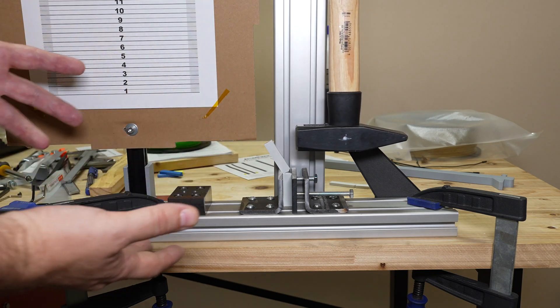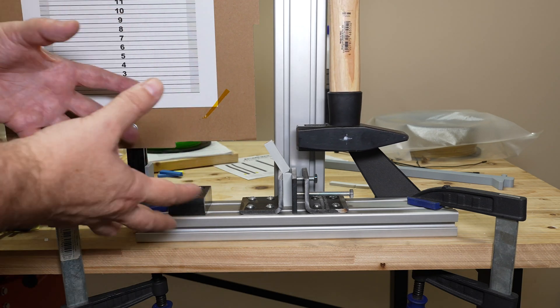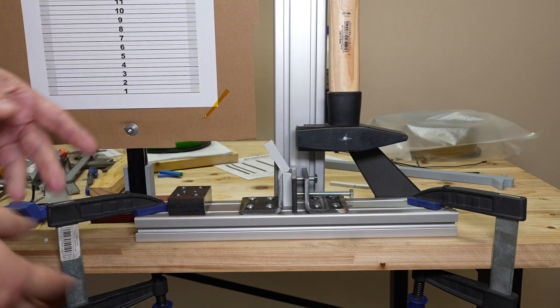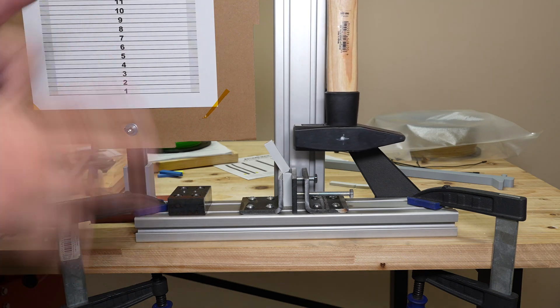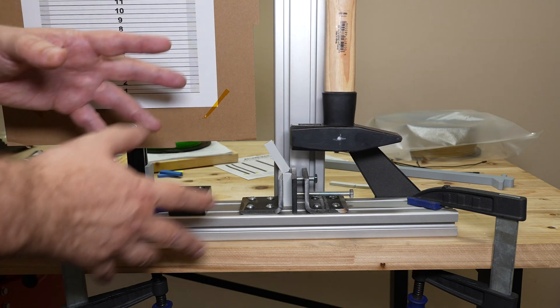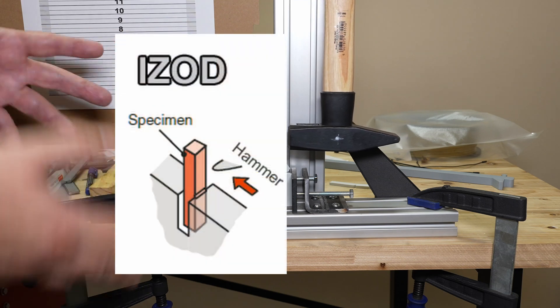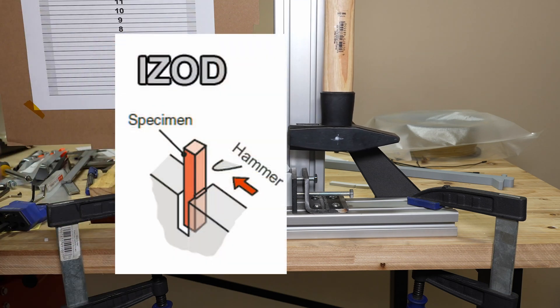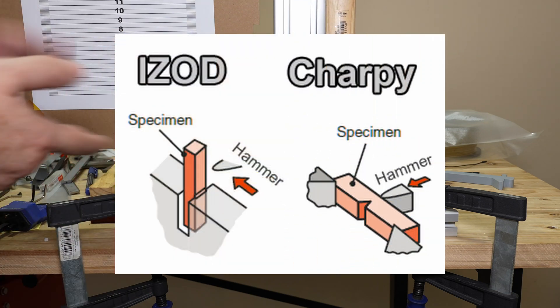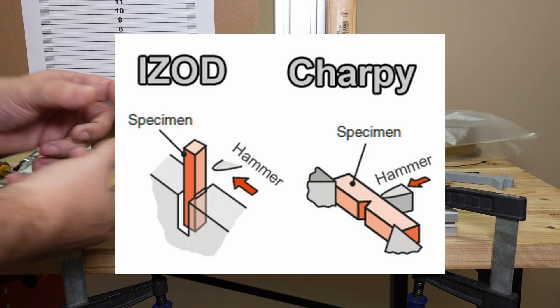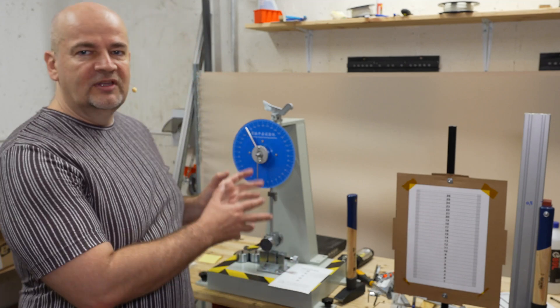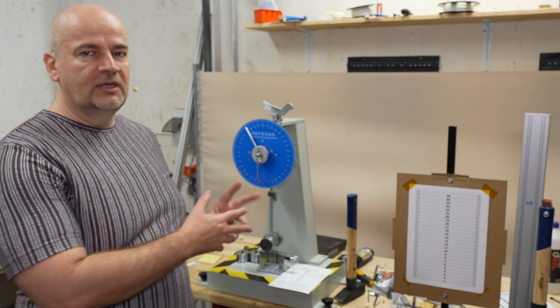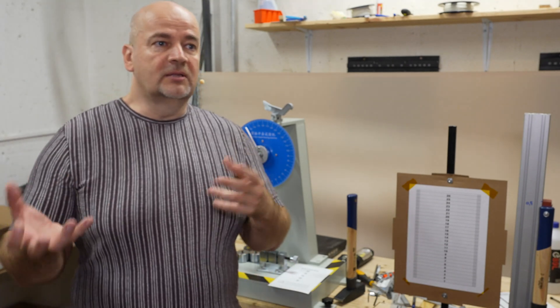Even then the difference would be very minimal. So my DIY impact tester is good for comparisons, but it is not good to use these numbers and compare them with the data sheets from the companies. But don't forget again that this is based on some kind of Izod impact test. Additionally, the companies are using usually the Charpy, and there we have supports from two sides and the breaking energies are even higher.